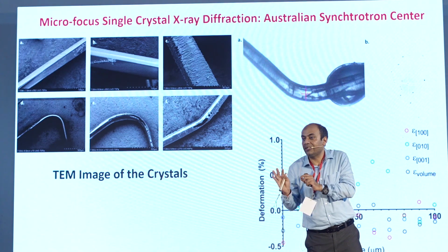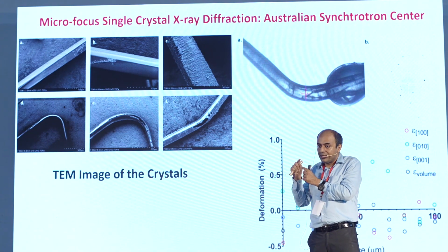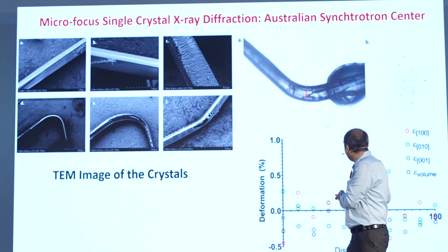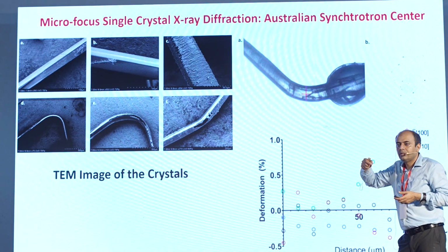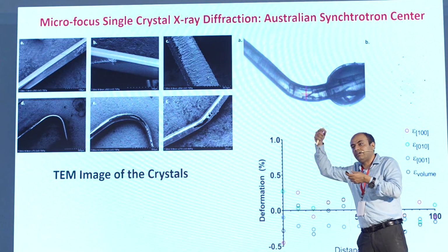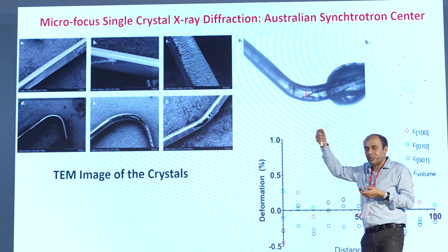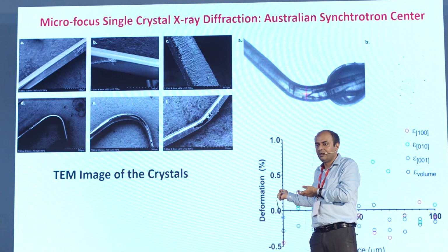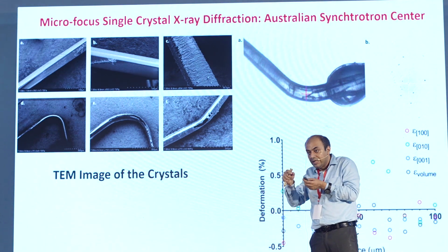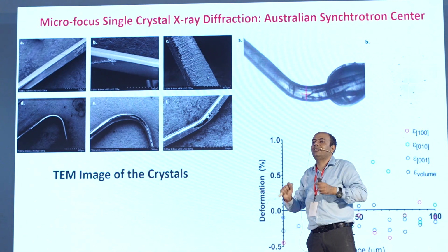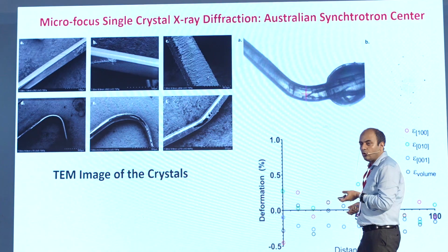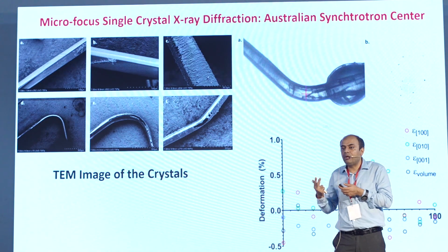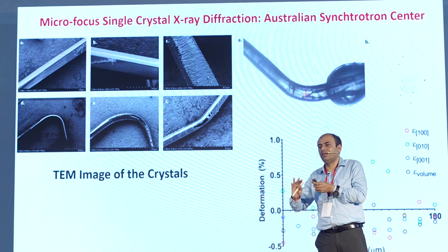Although the defect concentration is high, it is not yet so high that this very sophisticated mapping at the atomistic level, whereas that displacement is micrometer, this is at nanometer, angstrom. So we are probing deeper, and at that level the structure is still maintained. There is some deformation within, so within 1% is very good data. Beyond 1%, the structure would have changed.